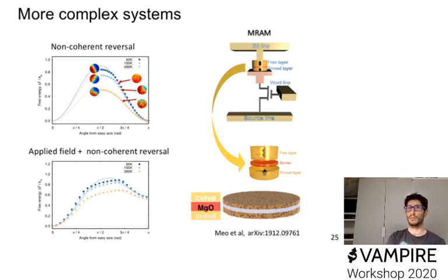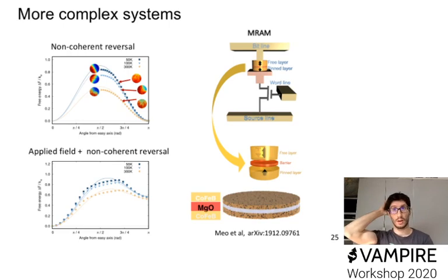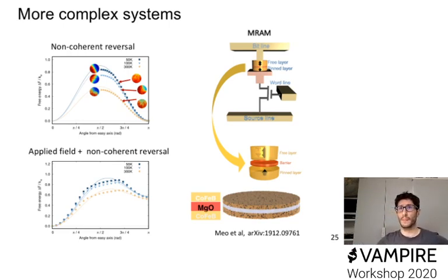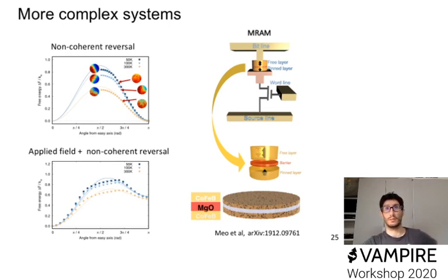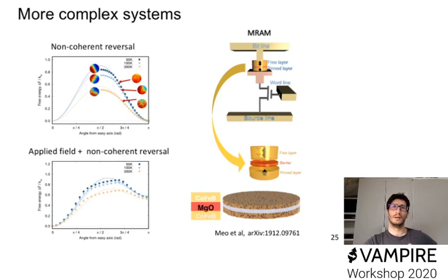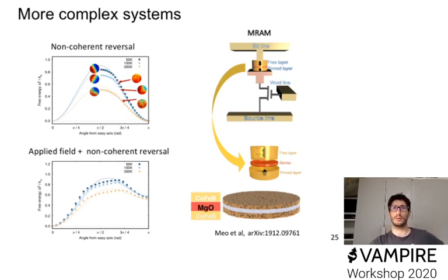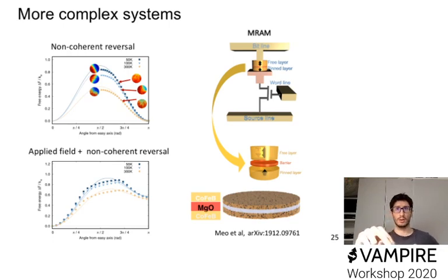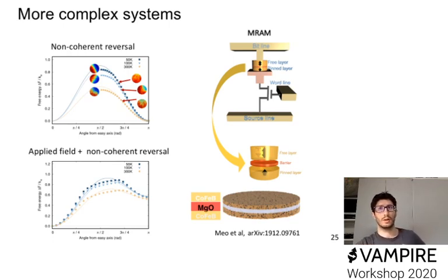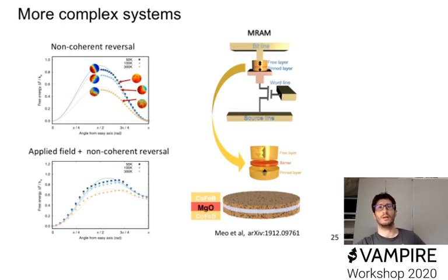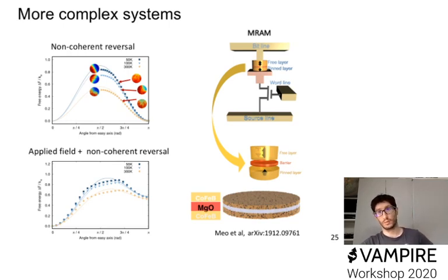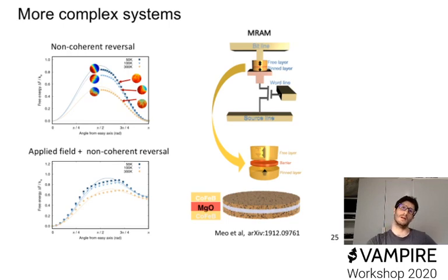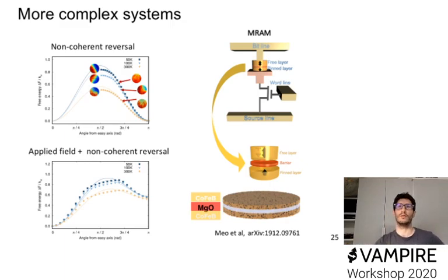Classically, you would have a flattening of your energy profile, meaning that your anisotropy is lower, and your energy barrier is lower, and these results have been obtained performing constraint Monte Carlo simulations on such systems. As you can see, you can obtain all these interesting properties, which I don't know, might be complex, especially if we compare with analytics, where the sine square of theta, we can see fails in reproducing the characteristic. And then, so where we have this non-coherent reversal, because the system is also large enough to accommodate two domains of reverse magnetization directions.